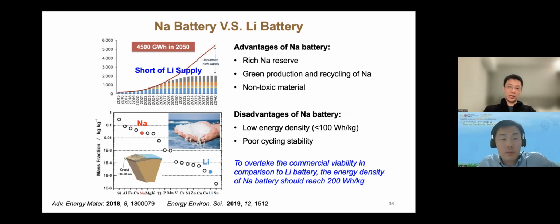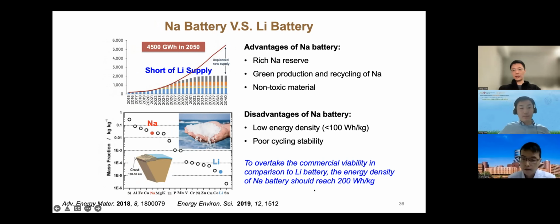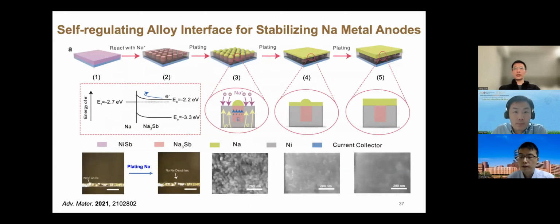So by the DOE, it was calculated that if you want to overcome this commercial availability comparable to lithium battery, the energy density of sodium battery should reach somewhere around 200 watt-hour per kilogram, which is a huge effort to reach, right? So in our case, what we found is that there's an interface made of nickel antimony, so NiSb, that